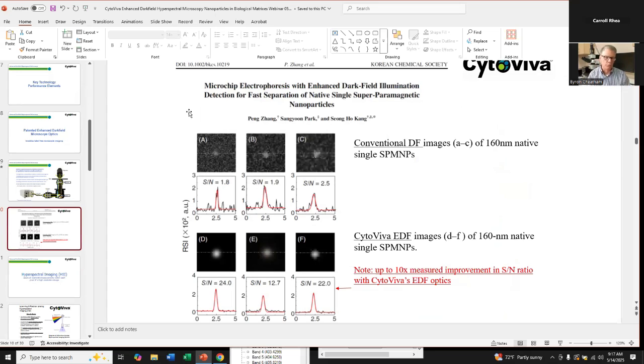This is a paper that was produced a number of years ago by a research group in Korea that had acquired these Darkfield optics, these enhanced Darkfield optics, to do microchip electrophoresis work. They had been for years using standard Olympus Darkfield optics, and they were able to get images such as this of these 160 nanometer iron oxide nanoparticles. By using the same microscope and just upgrading to the CytoViva enhanced Darkfield optics, they saw a dramatic improvement in signal to noise ratio, the ability to detect the scatter of the nanoparticles, and to be able to measure that. And when they measured that signal to noise ratio, as you see here, they measured about a 10x increase in signal to noise ratio.